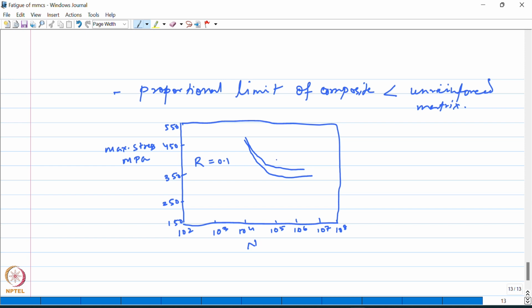Okay, so the upper one is for the composite and the lower one is for the unreinforced alloy. Okay, so here you can see that the fatigue life of the composite is higher, as I said before, or the fatigue resistance for the composite is better. This is because of the fact that the total strength in the composite is lower, right?